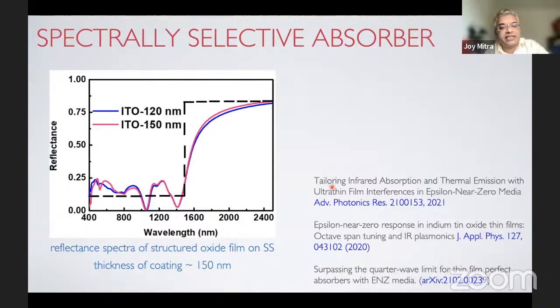What about spectral selectivity? Here we have the reflectance spectra of a structured oxide film on stainless steel with a coating thickness of 150 nanometers. And you can see the reflectance spectra of this structure. In spite of just 150 nanometers of oxide films, carefully tuned oxide films, what we see is that the reflectance is around 10% on average in the entire visible, and then suddenly goes up to 80% above a critical turn-on wavelength. And these are absolutely tunable by tuning the lambda ENZ, the thickness of the films, and so on.